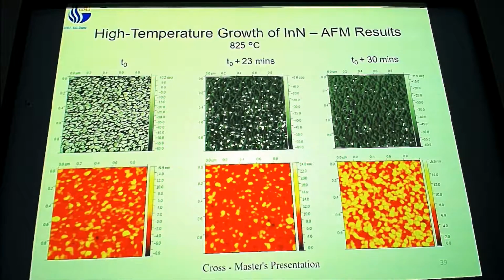I'm positing that this is the surface charge accumulation layer. It is known that in indium nitride, there is a surface charge buildup. And what this buildup does is, if you have an AFM, it actually messes with the interaction between your tip and the surface of the material. The sample's charged. And I discharged it by grounding it.